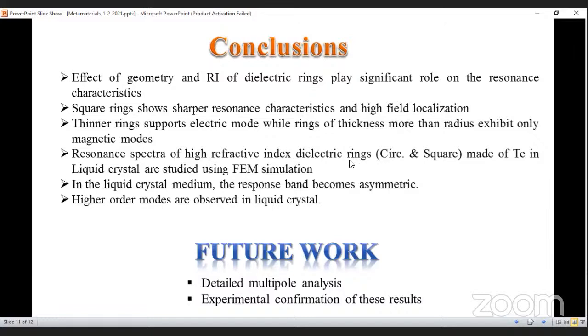Resonance spectra of high refractive index dielectric rings, circular and square, made up of tellurium liquid crystal, are studied using the finite element method. In the liquid crystal medium, the response band becomes asymmetric, and here we also observed some higher order modes. Our future work is detailed multipole analysis and experimental confirmation of these results.